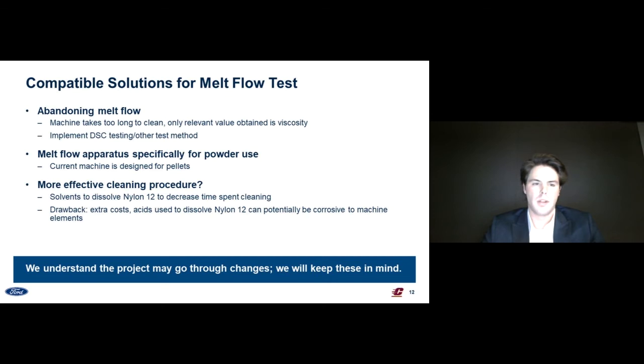And our last idea was to find out a more effective cleaning procedure. There's been some research into solvents to dissolve Nylon 12 to more easily clean the machine, but these solvents are acids that can be potentially corrosive to the machine elements. And Ford currently uses just a rag to clean the machine, and there's been research to show that that is mostly the most effective way to clean the melt flow machine. So instead of going with these other 2 options, we're going to decide to abandon the melt flow and pursue